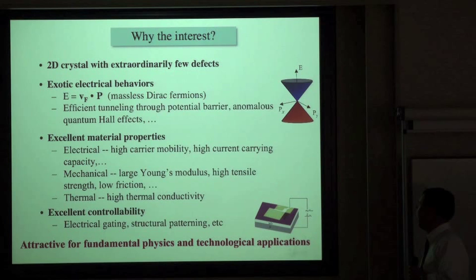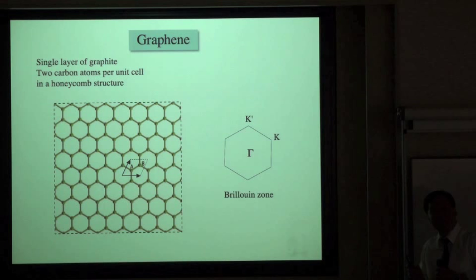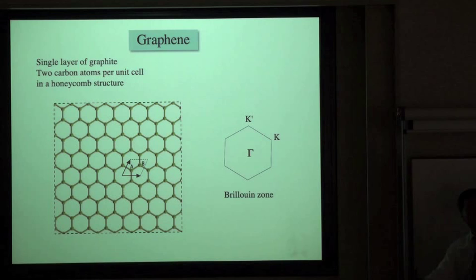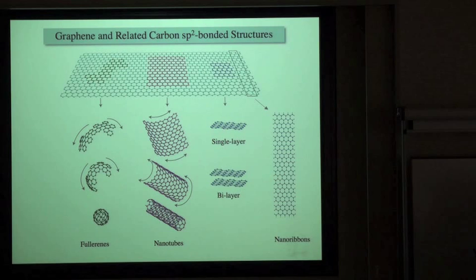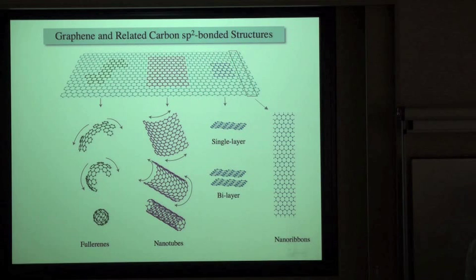The structure of graphene is very simple — it has only two atoms per unit cell forming a honeycomb structure. The atoms A and B form two interpenetrating sublattices, and the reciprocal lattice of graphene has a hexagon in momentum space. Graphene is also the mother structure of many nanostructures, including fullerene molecules, carbon nanotubes, single and bilayer graphene, and nanostructures such as nanoribbons. In today's talk, I will focus on the last three types of structures.